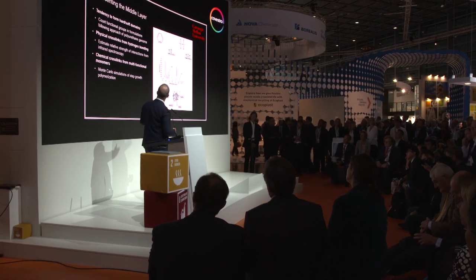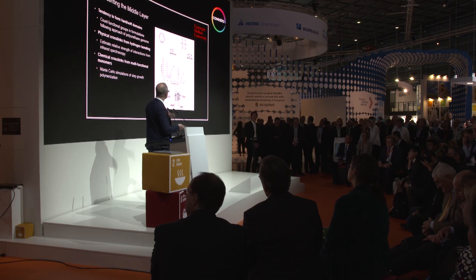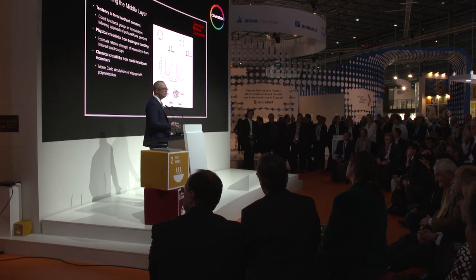And so what we've done is take an approach that mixes counting functional groups to start building predictive models of the microphase separation. We've done simple experimental measurements looking at infrared spectroscopy and shifts and peaks. And then we've also collaborated with Jim Thompson at Covestro in using some simulations that he has to predict what the chain architecture looks like. Each one of these factors tells us something about how the microstructure is changing and how that will affect the material properties of the system. What the algorithm does is take all this information and then start to build predictive models from them.